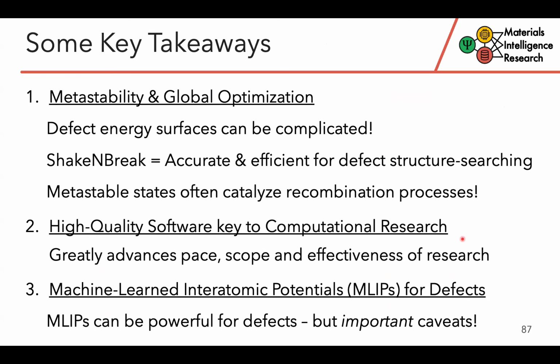Using up too much of my time, but just to summarize, I would say that some key takeaways are that metastability and global optimization is important for defects. Defect energy surfaces can be quite complicated, as we've seen. We propose ShakeNBreak as an accurate and efficient method for structure searching of defects. I'll say the highest quality software is key to computational research. So we've developed some of these codes like ShakeNBreak. Of course, other people in the field have developed very useful codes like PyDefect from the Kumagai group. And so they really do benefit research and us as a community. And last, we saw that machine learning interatomic potentials can be useful for defects. There are a number of different challenges in this area for using them more broadly for defects, but when used in the right way, they can be important.